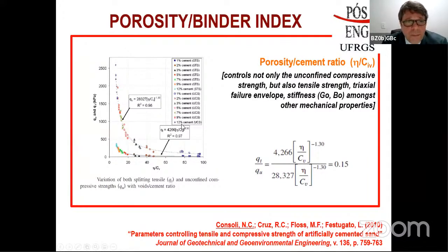And besides that, both give equations in which this part here is the same. So the only difference between tensile strength and compressive strength is a scalar in front of it. If we divide QT by QU, which means tensile by compressive, we get a scalar. And this scalar, of course, depends on the cement, on the soil, and so on. In this case, for this cement and this soil, it was 0.15. But you might have different values varying from 0.10 to 0.18, depending on the soil and the cement that you use.